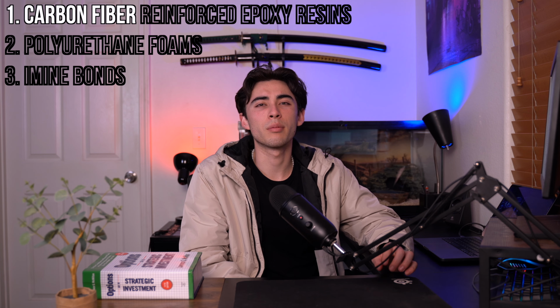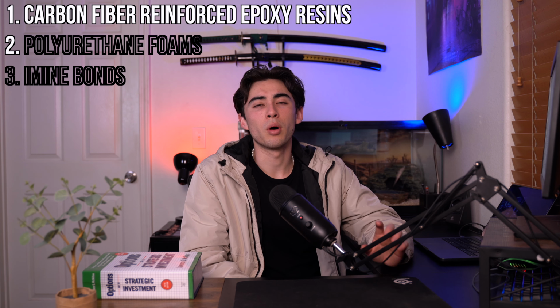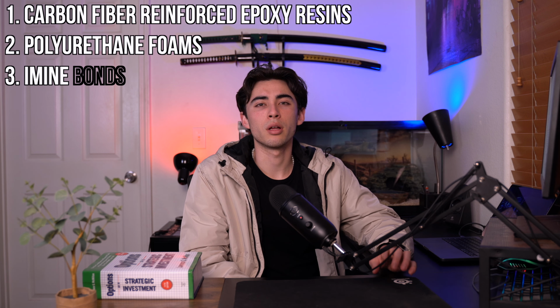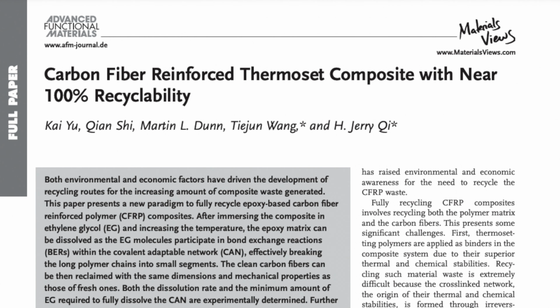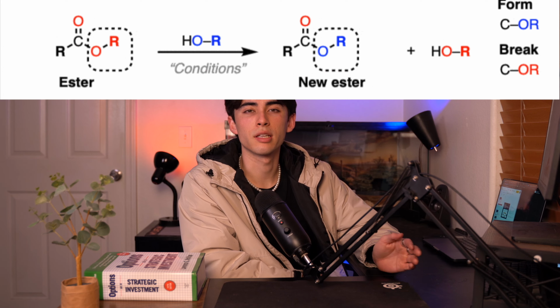Though covalent adaptable networks have been successfully implemented into many different systems, the 3 we are focusing on today are carbon fiber reinforced epoxy resins, polyurethane foams, and imine bonds. One such way covalent adaptable networks were investigated for recycling was in an epoxy-based carbon fiber composite. In this paper, Yu and associates were able to fully dissolve the epoxy resin in ethylene glycol at 160 to 180 degrees Celsius. The associative CAN was recycled via transesterification.